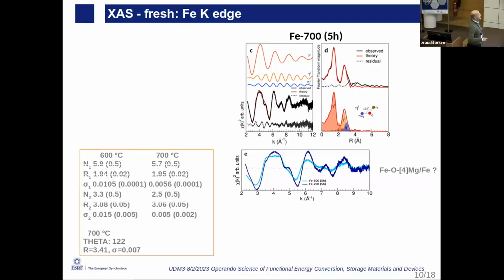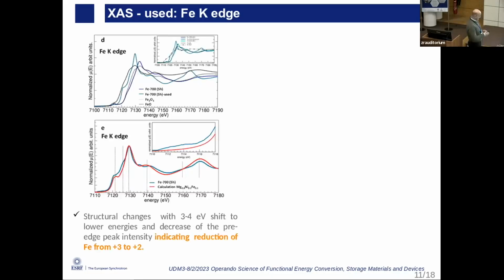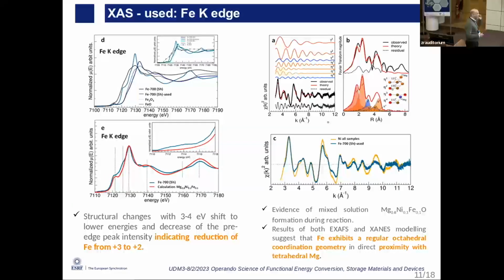The difference is clear when we look at the K space from the fresh and the used. So now we go to the used material. When you run the catalyst, we see that there is a reduction of the material: the iron gets reduced. Since we think that it goes inside the structure, again we model the iron inside the nickel magnesium oxide structure, and also in this case this works quite nicely. We have basically recovered all the main features, and again we tested with EXAFS analysis, and of course this matches the structure we wanted to check. But in this case, again, to have a satisfactory fit, we need to add this blue contribution, which is the iron that sees the magnesium, and the magnesium seems to be in a tetrahedral configuration.